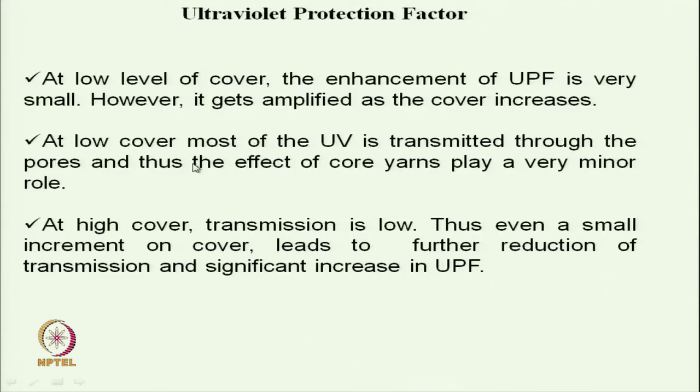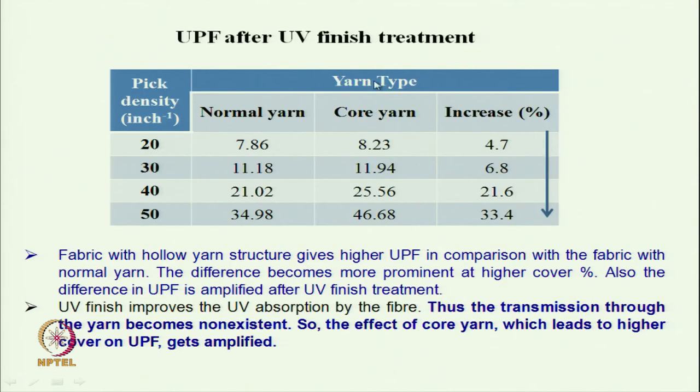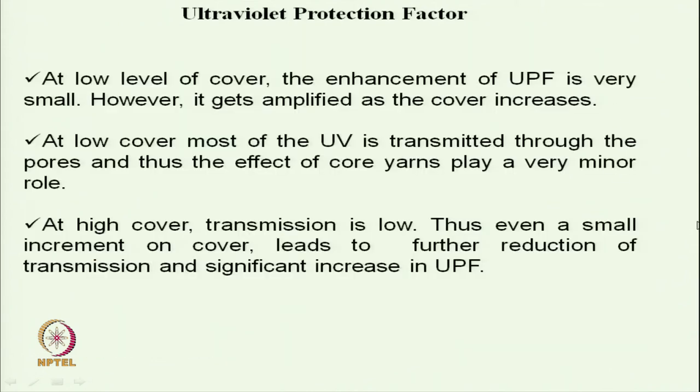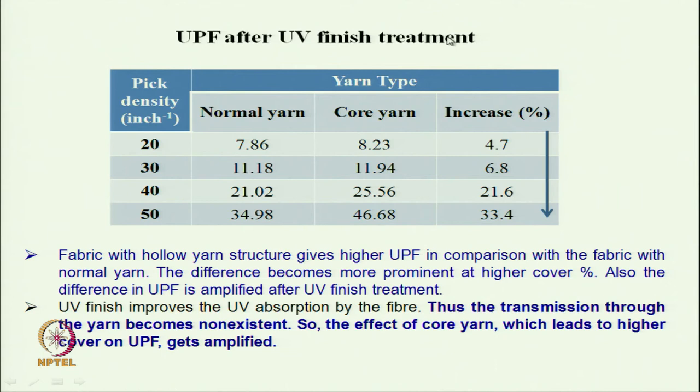At low cover, most of the UV is transmitted through the pores, and thus the effect of core yarn plays a very minor role. At high cover, transmission is low, thus even a small increment of cover leads to further reduction in transmission and a significant increase in UPF. With UV finish treatment, the increase is much higher than the untreated. Earlier it was the untreated fabric, but here this is UV finish treatment.